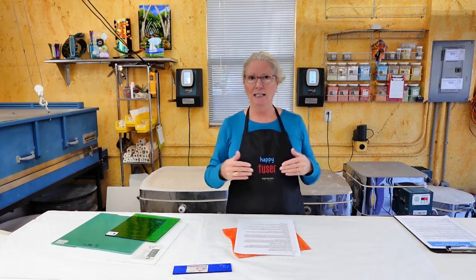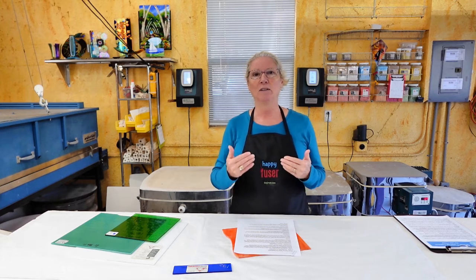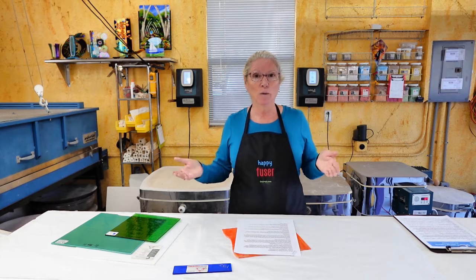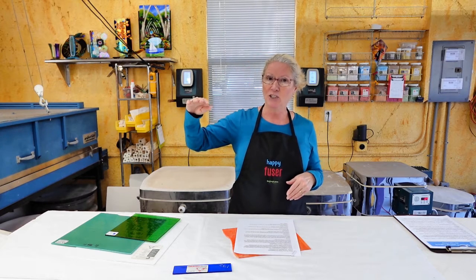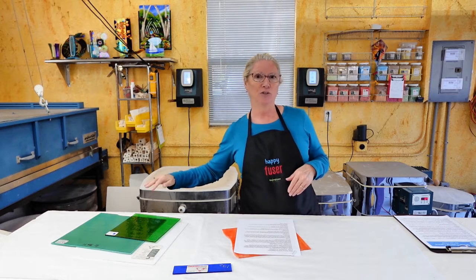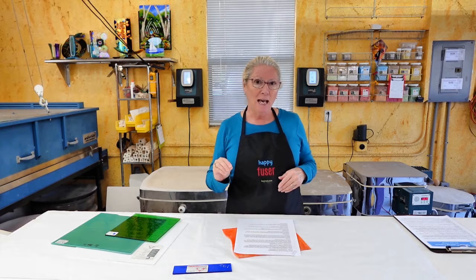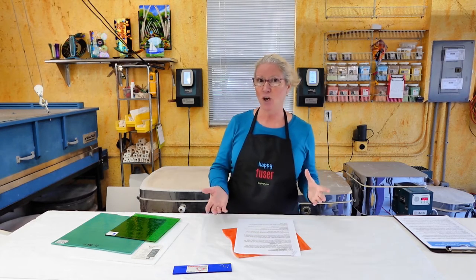So imagine you're taking these materials, you're forcing them together, creating stress. We want to relieve that stress, and that's called the anneal phase, or annealing, or when you anneal your glass. You just hold it for a period of time, relieve that stress, and then lower the temperature gradually back to room temperature. Annealing is really important because at that point, your glass is already fired together. You already have the beautiful piece of art.